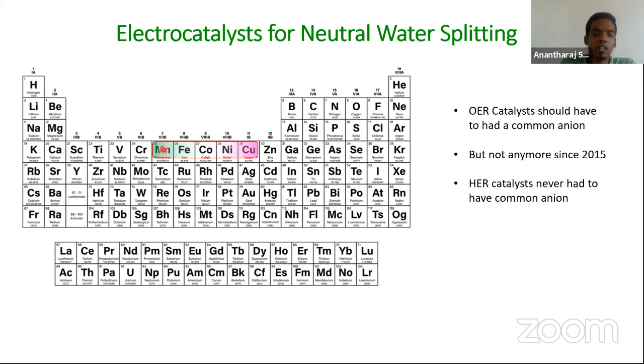Fortunately, these 5 metals in the 3D series perform relatively well for both water oxidation and water reduction. So these are the choice of metals that we have for designing our catalyst in neutral water splitting. The main reason is that in the neutral water splitting process, these metals have appropriate energy of interaction with the intermediates that are to be formed in both hydrogen and oxygen evolution reactions near neutral waters.